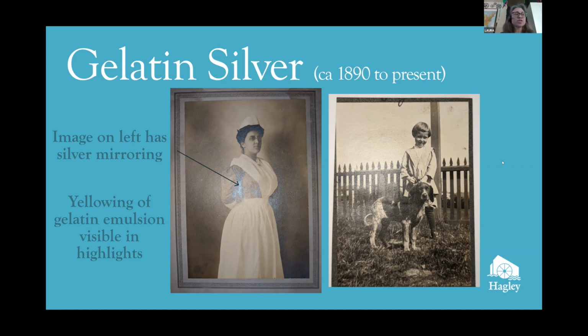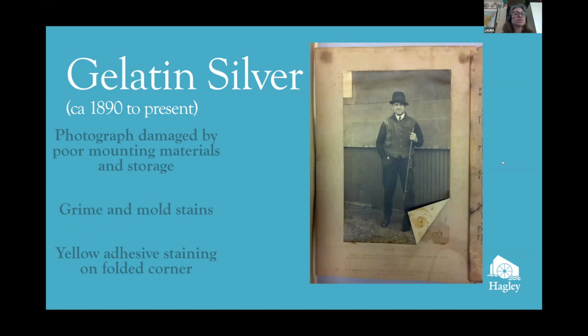The image material of silver gelatin prints, being silver metal, can fade and turn brownish by pollutants. Pollutants might include outdoor sources like car exhaust or indoor sources like varnishes, paints, and cleaning chemicals used around the house. The gelatin silver image may also form a shiny layer of silver mirroring if they're exposed to humidity and pollutants. Humidity allows the gelatin emulsion to swell enough to allow pollutants access to the silver particles with which they chemically interact in an oxidation reduction reaction. The silver metal particles then migrate to the surface.